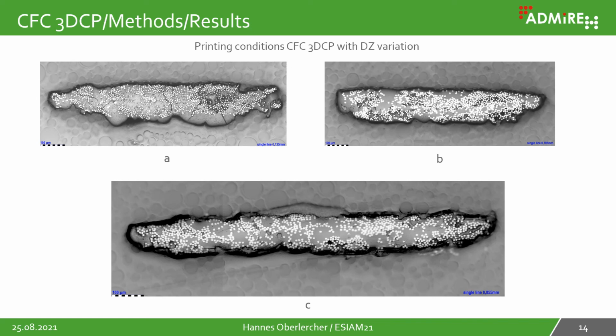Here you can see the results of the first experiment. Sample A shows well distributed fibers in the matrix, but the layer height over the width of this single line is not really constant. In sample B, the fibers are well distributed with a low content of cavities, and the layer height is constant over the width. The best result shows sample C with the highest consolidation pressure. The fibers are very well distributed in the matrix, with a pretty low content of cavities, and the layer height is also pretty constant over the width.